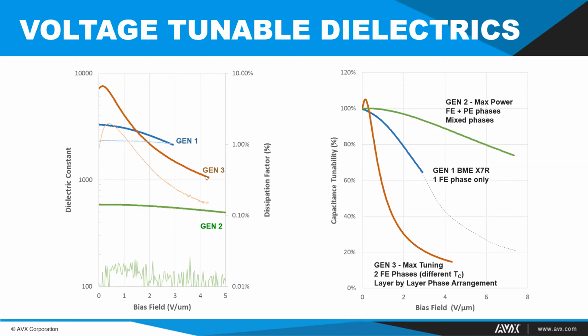On the other hand, a Gen 3 type material, which has a larger composition with more diffusion of the dopants throughout the material, exhibits a much steeper curve. This material would require less tuning voltage, although the losses might tend to be a little bit higher depending on the temperature at which you use it. So there are challenges in using any one of these materials. The biggest thing is being able to control not only the voltage coefficient, but both the losses and the temperature behavior of the material too.